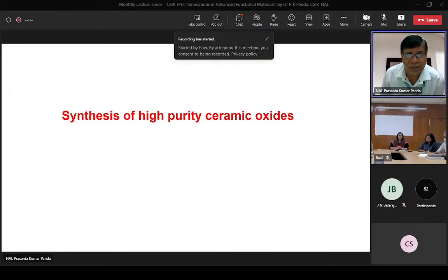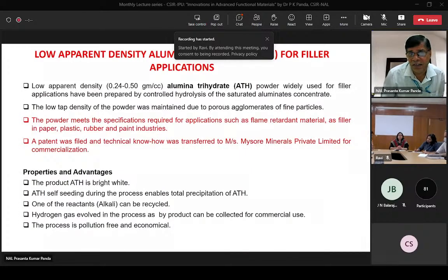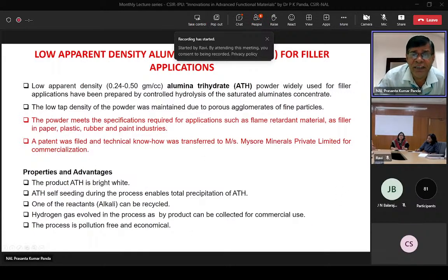Then coming to synthesis of high purity ceramic oxides, this is work which was carried out before 2000, at the beginning of my years at NIIST. One such work was there. I interacted with NALCO, National Aluminium Company, in Bhubaneswar, and they said that ATH is a promising material. They had given a sample, and we thought, okay, ATH is very easy to prepare. When you precipitate ATH, you get aluminum trihydrate, from aluminum salts like the chloride, with ammonia.